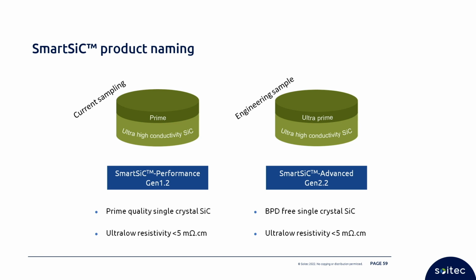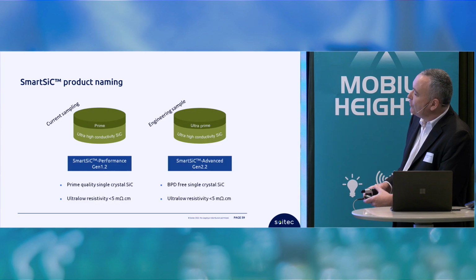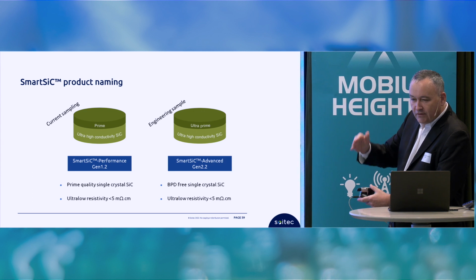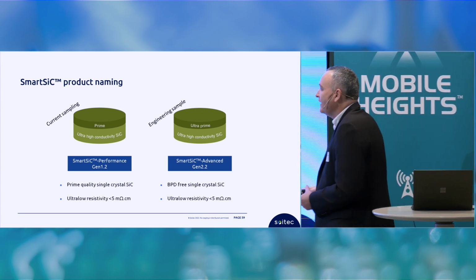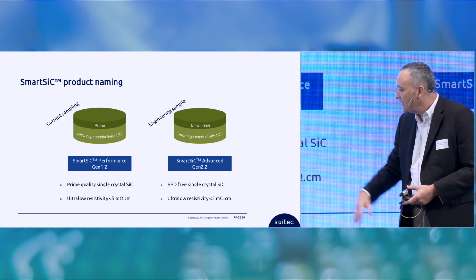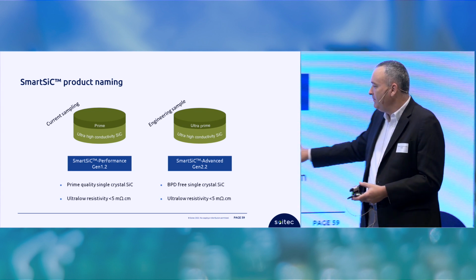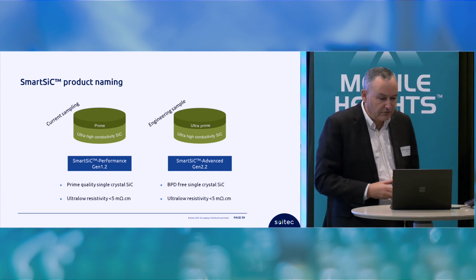What is similar between the two products is, as the handle material, we have an ultra-low resistivity, less than 5 milliohm centimeters, typically a factor of 10 improvement in the resistivity versus a conventional mono SiC. So a strong improvement in the electrical performance. On top of this ultra-high conductivity wafer, we transfer a thin layer of mono SiC, prime quality mono SiC for SmartSiC Performance, and even a BPD-free single crystal for the SmartSiC Advanced.